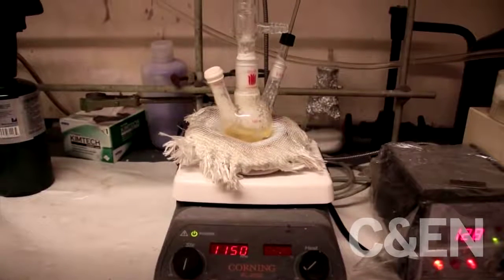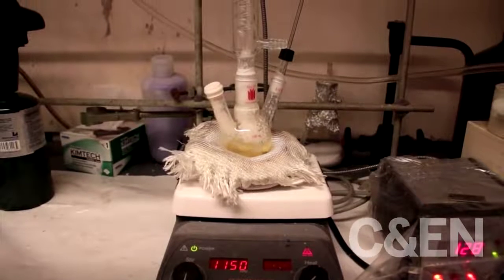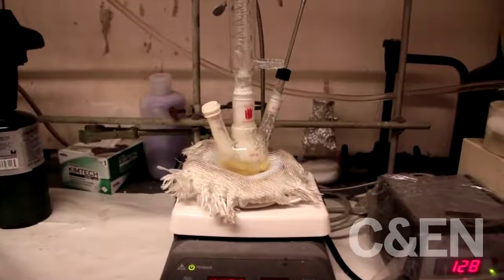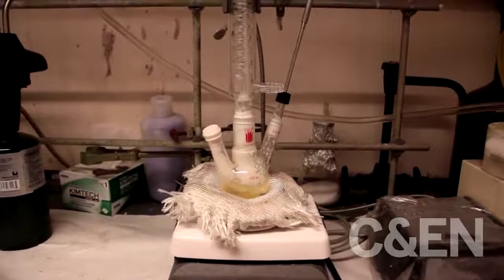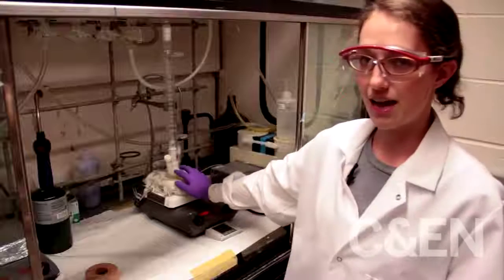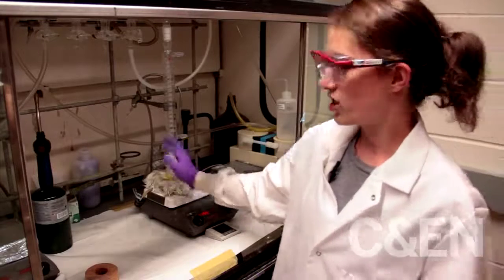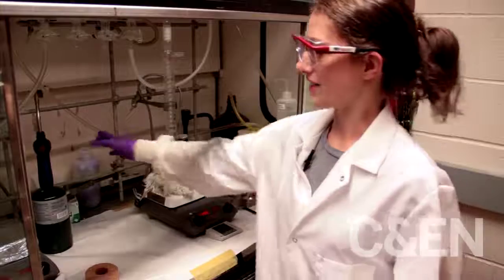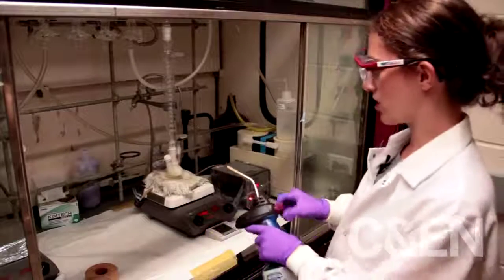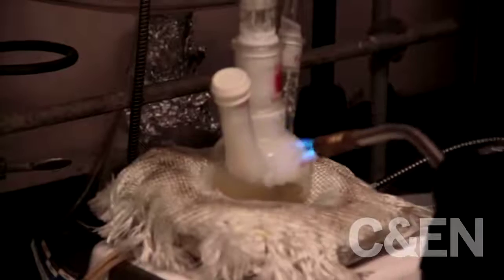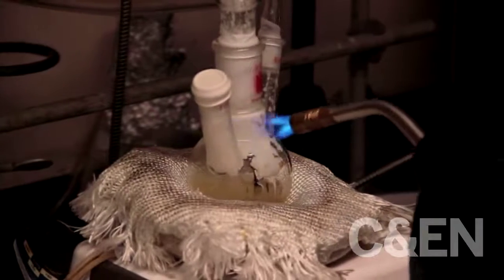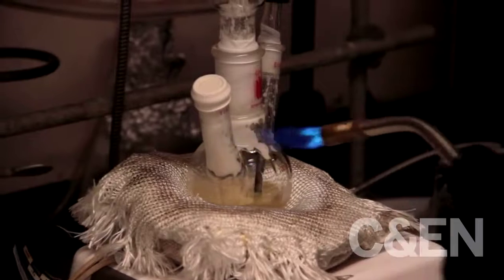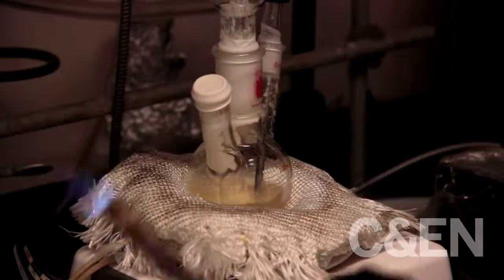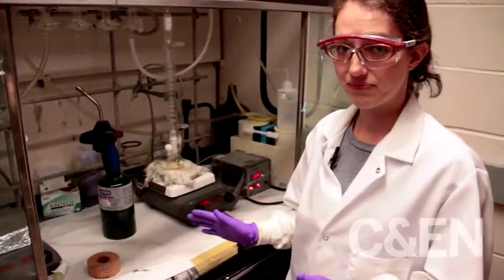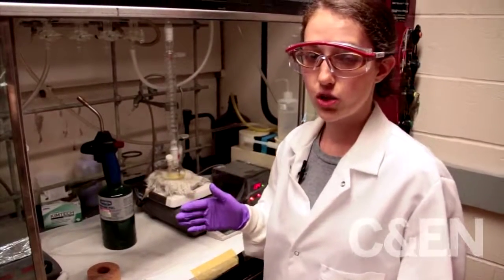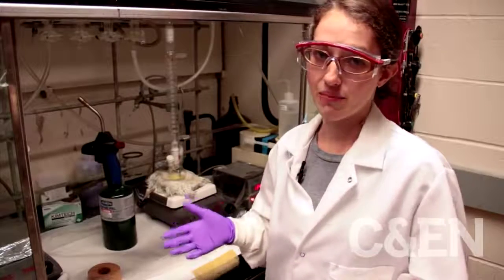And then we heated that up again until it all melted. And we have been putting it under a vacuum to get rid of all of the water inside. The first step, if you can see, there's some accumulation of the cadmium oxide and stearic acid on the wall. So I just need to heat that up to melt it off so it falls back down. So I'm just going to use a handy blowtorch. And you can see as I'm heating this up, it's falling back in. I don't want to heat it up too much, so try to go slowly. So now that that's ready, I'm going to go and head over to make the selenium for the injection.